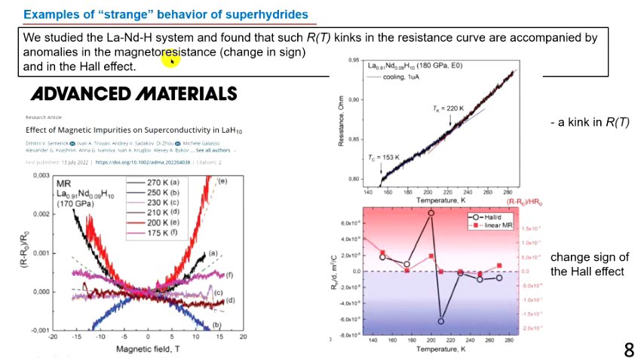Recently, we studied lanthanum neodymium hydrides, and the paper about this system is published in Advanced Materials this year, 2022, and we found that the kink in electrical resistance, this anomaly in temperature dependence of electrical resistance, is accompanied by anomalies in magnetoresistance. Magnetoresistance changes sign above 200 kelvins, and at the same time, we saw anomalies in the behavior of Hall effect. It also changes its sign around 200 kelvins, exactly in the same place where this kink is observed.